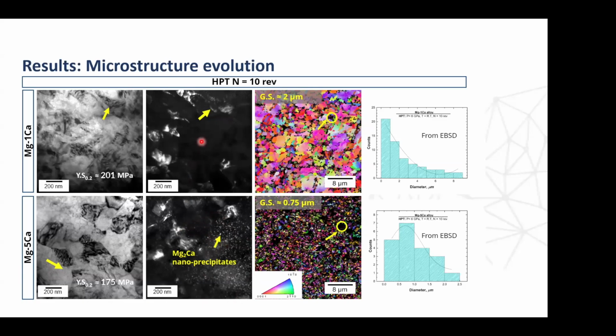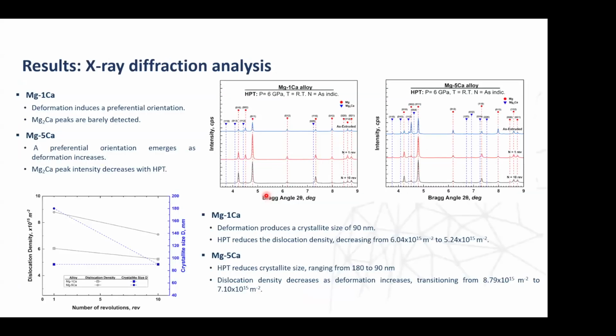So at the deformation that we did, which is 10 turns at 6 gigapascals, the microstructure is still heterogeneous. So we are looking forward to increasing the pressure, or probably increasing the strain, or using large form factor samples, so that we don't need to increase the strain so much, or the number of turns. With a larger sample at sufficient pressure, we can probably get a more homogeneous grain size. But nonetheless, we do see deformation strain in the microstructures.